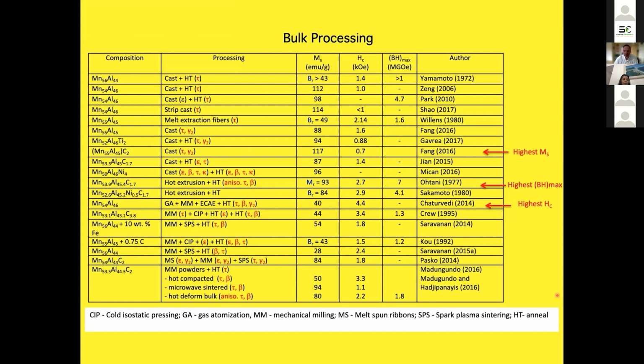People have also done bulk processing, as have we, and again, they use these different methods to produce particulates in some cases, and then use various methods to compact them, either cold isostatic pressing or hot compaction. In some cases, material is simply cast and heat treated, or sometimes it's extruded as well, so hot extrusion followed by heat treatment. And again, the thing I wanted to point out is that the work that produced the highest saturation magnetization is not the same as the ones that produce the highest coercivity and BHmax. So again, the optimum processing has not really been figured out yet.